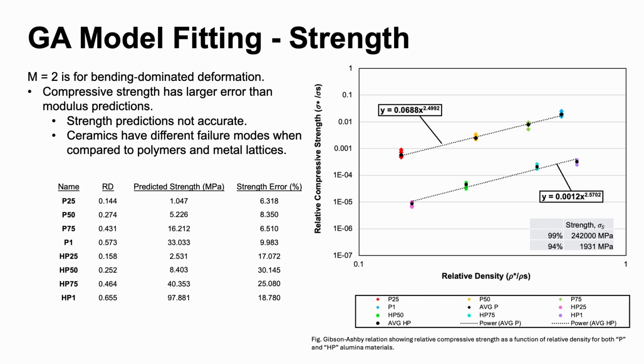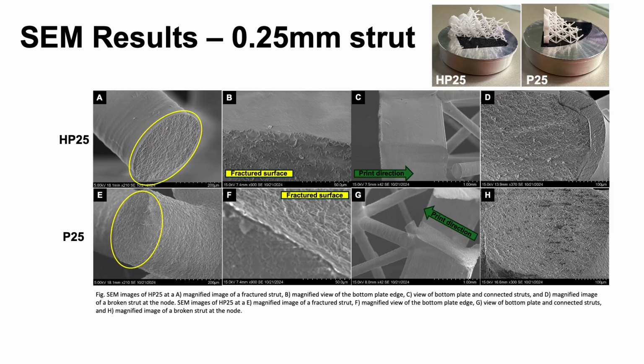It is possible that the fitting of the strength had a higher percentage error because of the different fracture behavior exhibited by ceramic lattice structures when compared to metallic and polymer materials. Ceramic materials do not yield, they just reach a maximum strength. So SEM was used to look at the fractured surfaces of the 0.25 millimeter strut lattices.